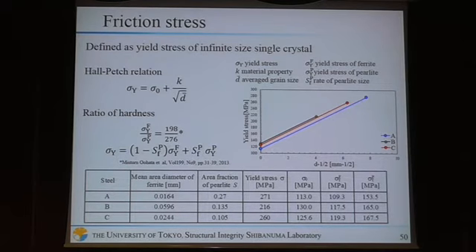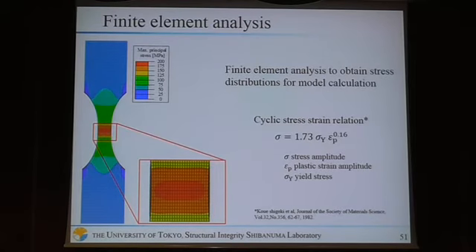The friction stress in this model is defined as the yield stress of an infinite-sized single crystal. Hall-Petch relation and ratio of hardness are used to calculate this friction stress. The result of calculation is on this table. Finite element analysis is conducted to obtain stress distribution for model calculation. In FEM, the cyclic stress-strain relationship is used.